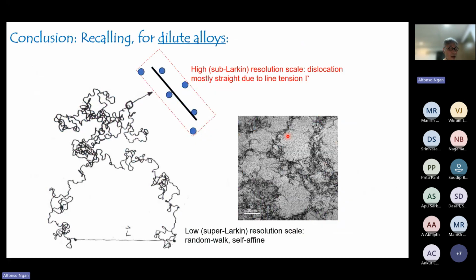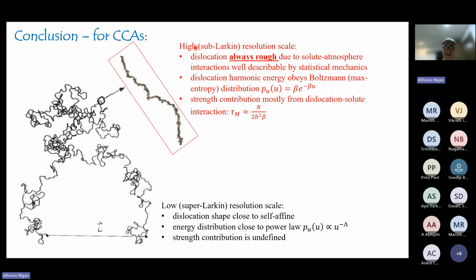So I come to my conclusion now, which is about 1 hour from the beginning of this talk, recalling that for dilute alloys, we have the Larkin transition, all right? But the transition is from, on a low resolution scale, a random walk behavior, into a high resolution scale, a straight dislocation line behavior due to line tension. That is for dilute alloys. For CCAs, the low resolution is the same. It is still self-affine, but for the high resolution, we don't have the straight behavior, but instead it is always a rough shape for the dislocation.